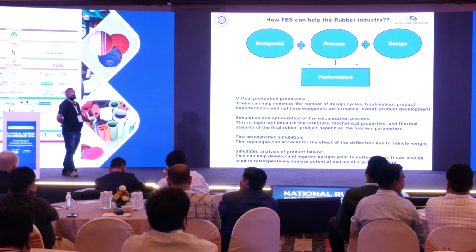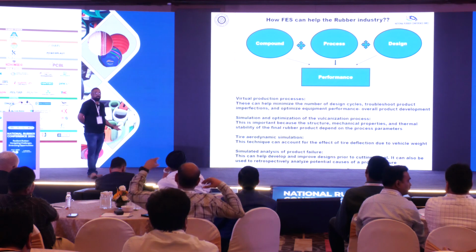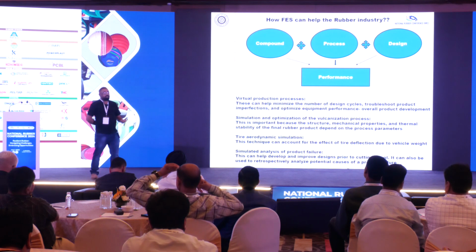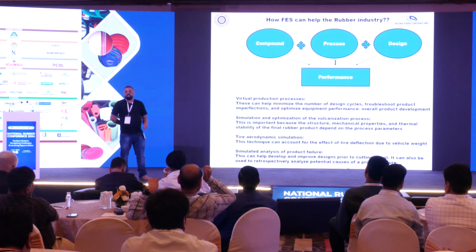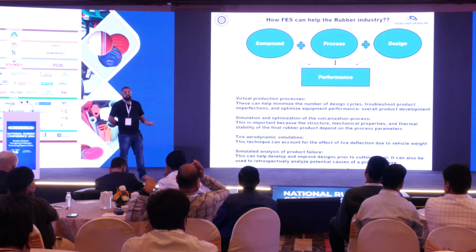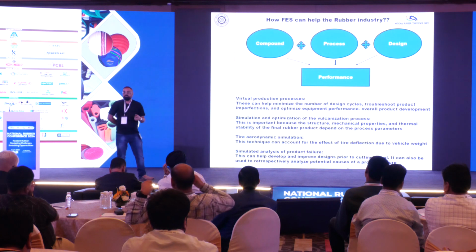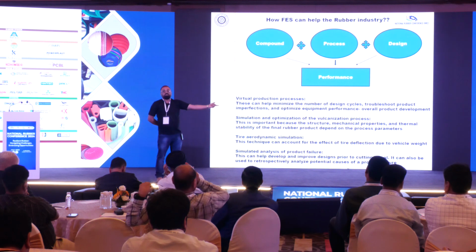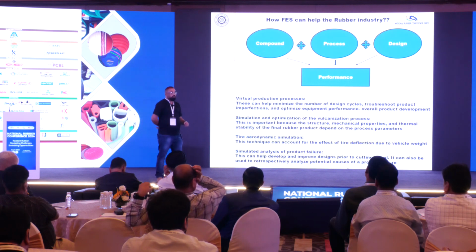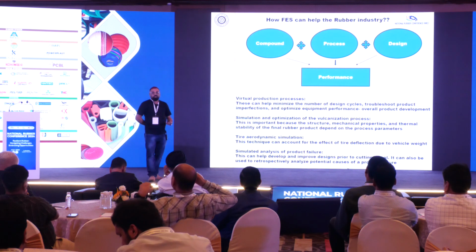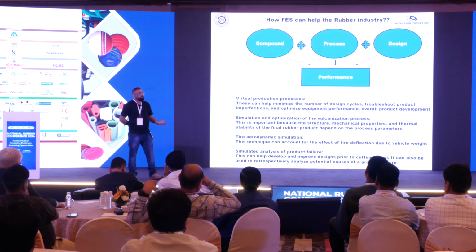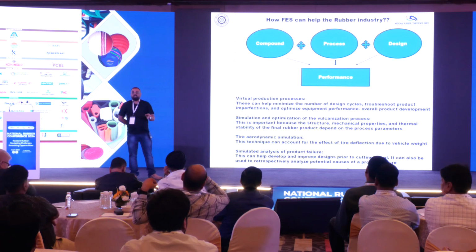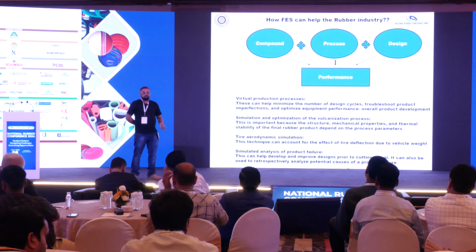Simulation and optimization of the individual process can be done as well, as I was mentioning, for vulcanization. How do we do this curing study in ODR, MDR, whatever? We do the study at say 140 degrees, 145, sometimes 160. We maintain that temperature for the entire period, so it becomes an isothermal process. But when you go for actual vulcanization, the process does not remain isothermal because rubber is a bad conductor of heat. If you put carbon black, the conductivity would increase, but it will never reach the level of a conductor. So the process never remains isothermal. It becomes non-isothermal.